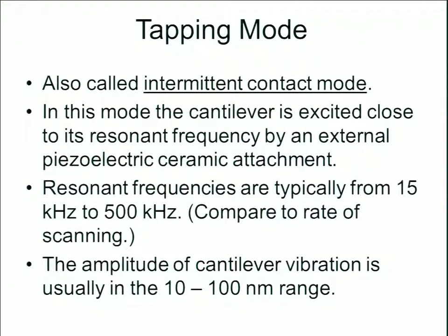This is an extremely fast frequency of oscillation, especially compared to the rate of scanning. Our last scan was at 2 Hz, while this can be as high as 500,000 Hz. The amplitude of vibration, although the frequency is very high, is usually in the 10 to 100 nm range.